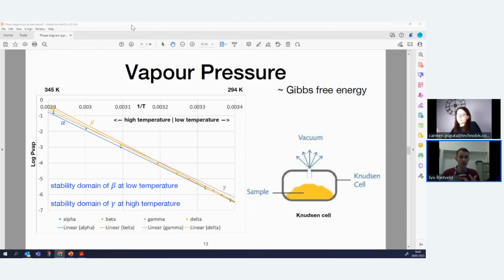So you can see that really at room temperature, alpha and delta basically have the same stability, thermodynamically speaking. And you can also see that the beta form comes in falling down rather steeply and must be crossing all those other forms at low temperature. So the beta form must be stable at low temperature. These things you can see from these vapor pressure measurements.